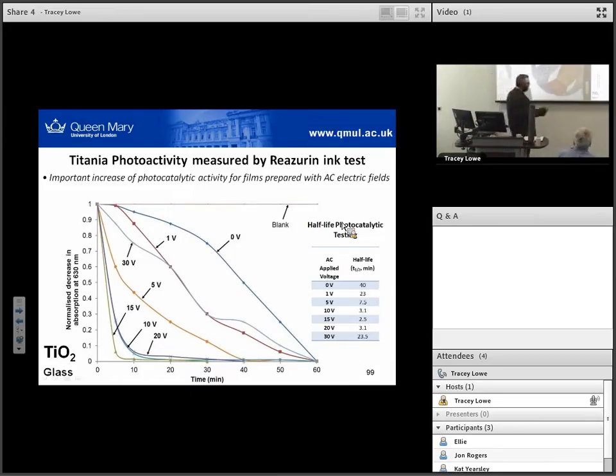So if you look at the 0 volt samples, this is a film made with no electric field, and then you look at some of our electric field samples, you can see clearly that we have a much quicker destruction or oxidation of this ink.